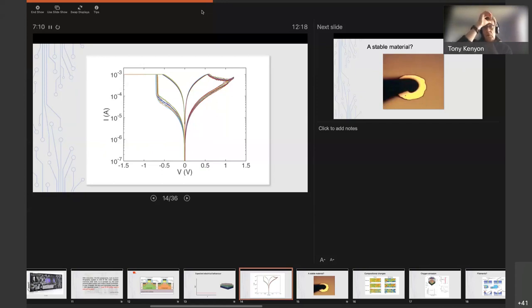Now, you do have to worry a little bit about diffusion of metals. If you use copper or silver, they diffuse very readily into oxide, so you probably want to avoid those. You then want to think about the electrochemistry of that oxidation process, and the oxygen affinity, the ease with which you can oxidize the top and bottom electrodes. You want to have different oxygen affinities, ideally very different. But unfortunately, if you have very low oxygen affinities, those metals tend to be the noble metals like gold and platinum and palladium, and they're very expensive, and gold certainly you wouldn't want to have in CMOS. So there are often compromises to be made there.